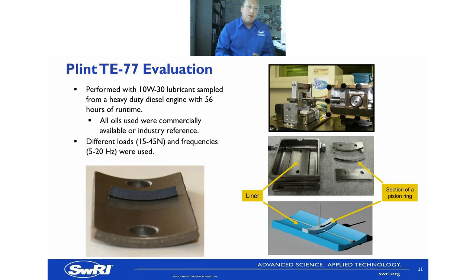Now, what we do there is we take a real piston ring after it's been coated and real liners, and we cut those up into the sample parts that you see on the right-hand side image there and the left, the big image. And we put oil in there and we reciprocate under different loads and different frequencies. And what we do is we measure the friction coefficient.